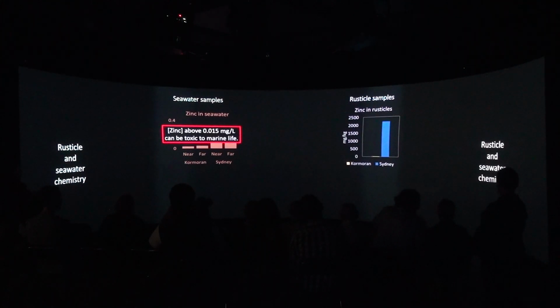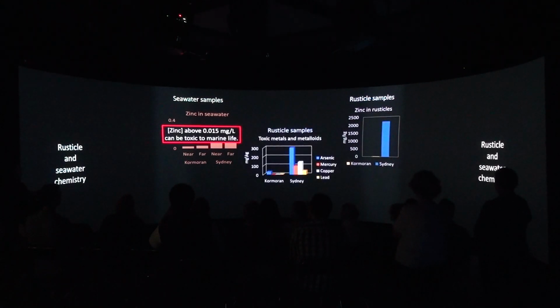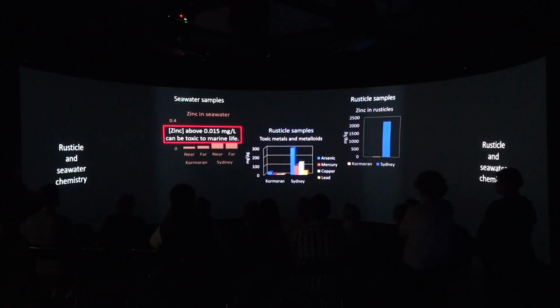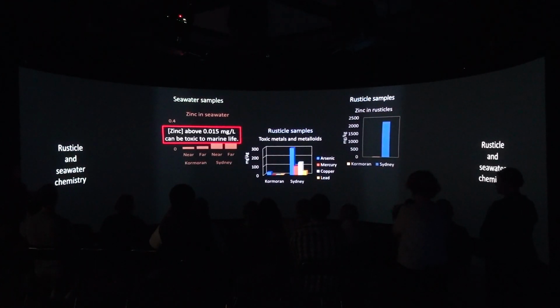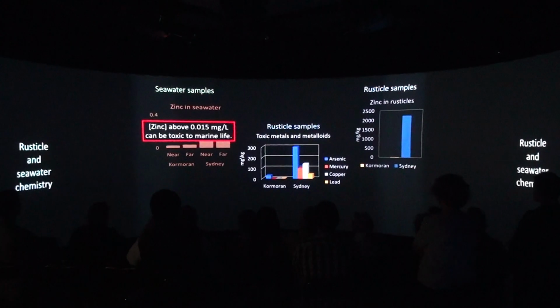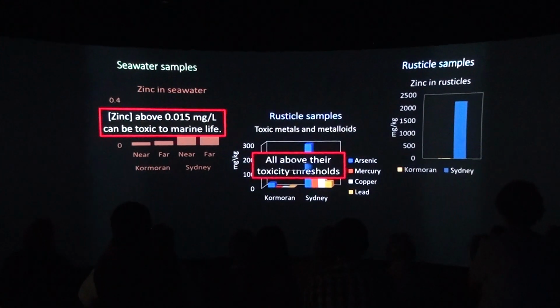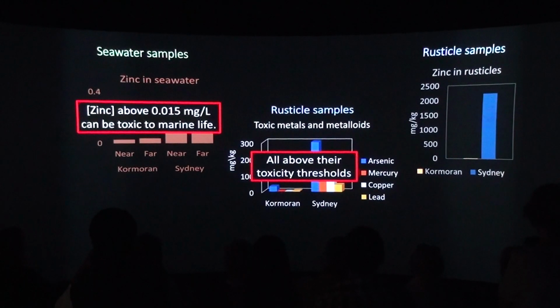But then after this, yes, zinc is toxic, but what other toxic things can be present in the rusticles? We didn't have any more seawater samples to analyze, so we had to continue with the rusticle samples, and we found that yes, they are really, really toxic. They have really high amounts of arsenic, mercury, copper, and lead, but the Kormoran had lower concentrations of them than the Sydney. And that may be related to what Andrew was saying, that there was more life and anemones in the Kormoran than in the Sydney. The Sydney is just a really toxic environment, and these are all above their toxicity thresholds.